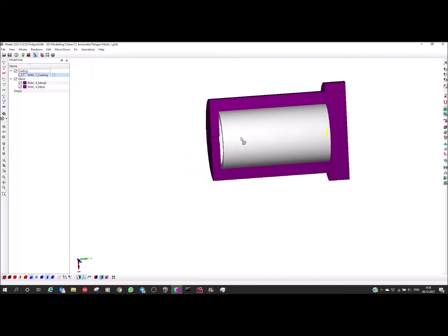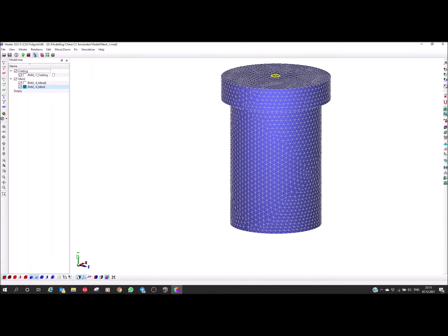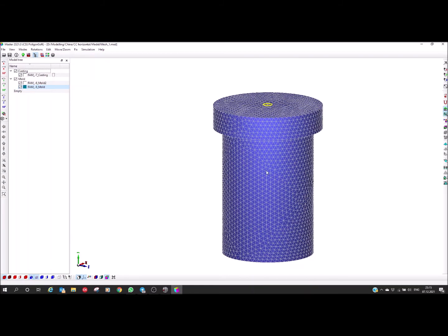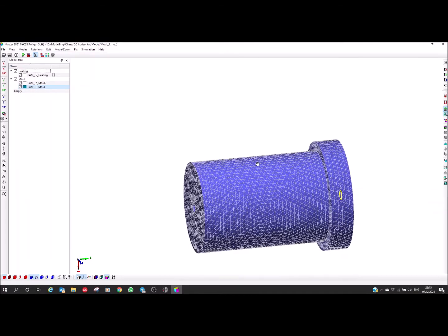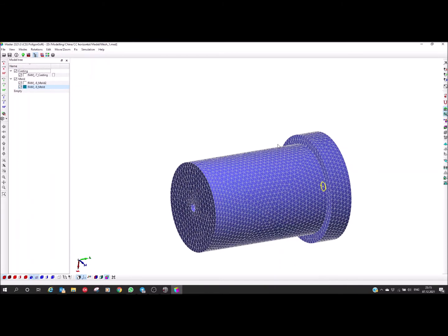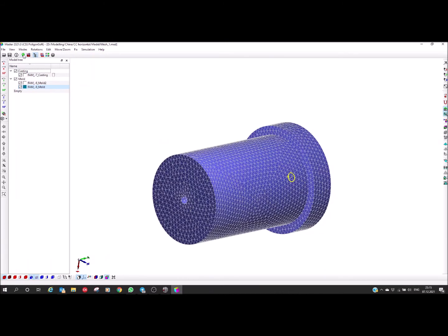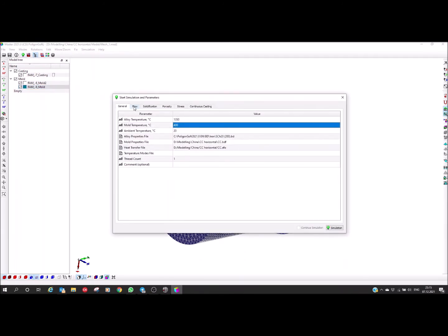and iron casting. So as we use in PoligonSoft gravity vector direction against y-axis, but in our case in horizontal centrifugal casting, the right position of the geometry is not like this, but like this. So we can't simulate filling, but we can simulate solidification, and we can simulate stress, and I will show how to do it. Go to the Start Simulation Parameters window, and on Flow tab, this parameter Enable Flow Model must be switched off.